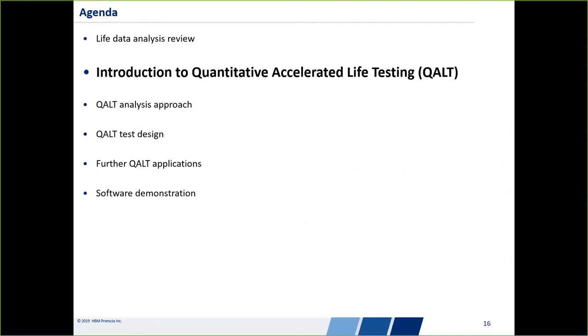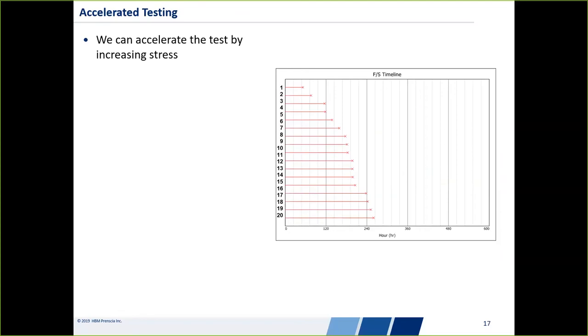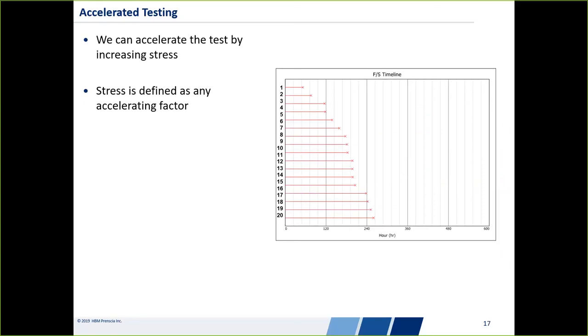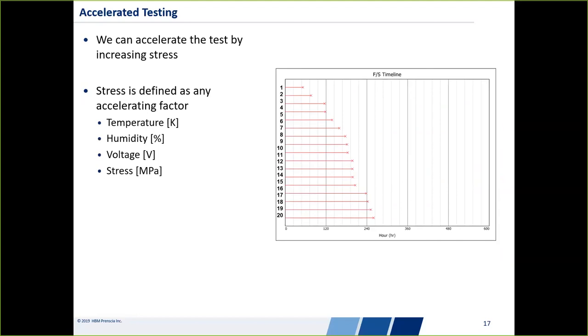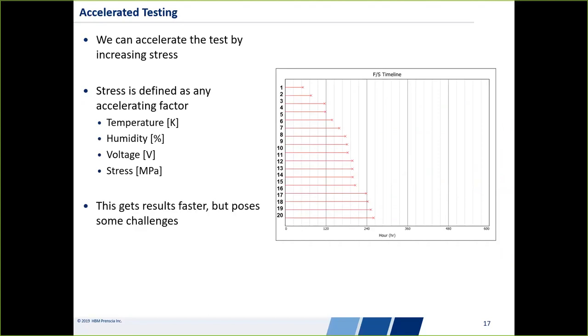The idea behind accelerated testing is that we can make failures occur faster by increasing the stress. On a timeline, all 20 parts have failed by about 250 hours — done just by increasing the stress. When I say stress here, I don't mean only mechanical stress in megapascals, but any accelerating factor such as temperature, humidity, voltage, or current. Increasing temperature or humidity would make parts that fail by corrosion fail faster, for example. So we've got results faster and can fit a distribution, but there are challenges in translating that into usable reliability results — that's what we'll talk about and how ALTA can help address them.